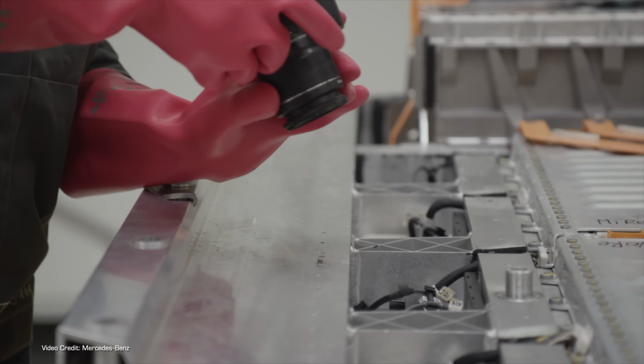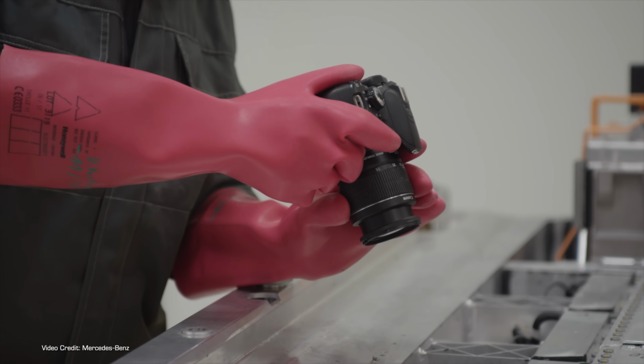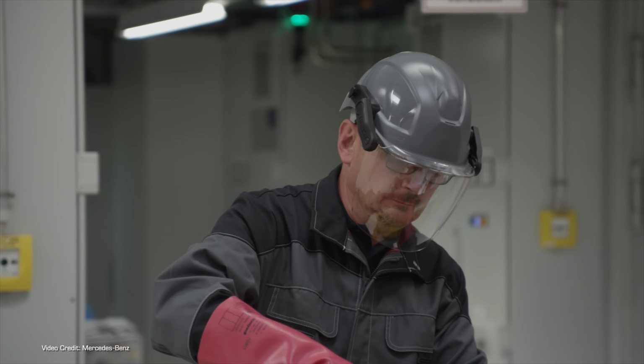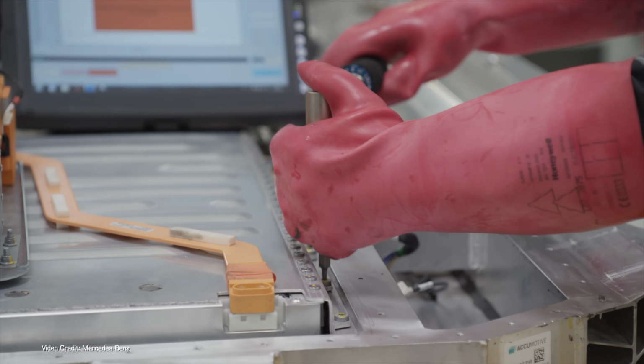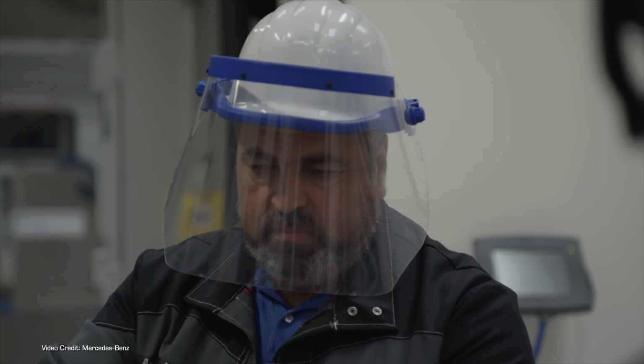This could be a fault in the cell design, which thankfully is rare but can happen from time to time, a contaminant in the cell, as happened several years ago with a whole host of battery packs destined for Mitsubishi i-MiEV and Outlander PHEVs, a problem with raw cell materials, or as we discovered with Hyundai and LG Energy, a misalignment in one of the machines on the cell production line. Because these deficiencies can be so tiny and so hard to spot, and because when cells do fail it can lead to their near complete destruction, it takes far longer to detect and remedy a physical problem with a battery pack than it might be to detect problems with other vehicle components.